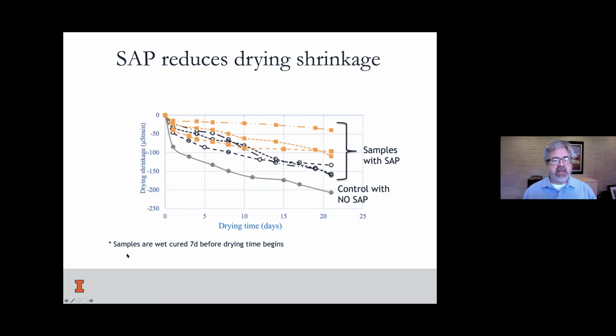Here's some samples that were wet cured for 7 days before 0. So this is a standard drying experiment where 0 is now a 7-day age, and we're drying samples. The control with no SAP has considerably more drying shrinkage than what we saw from any of the ones with SAP. That's our main benefit here coming through.